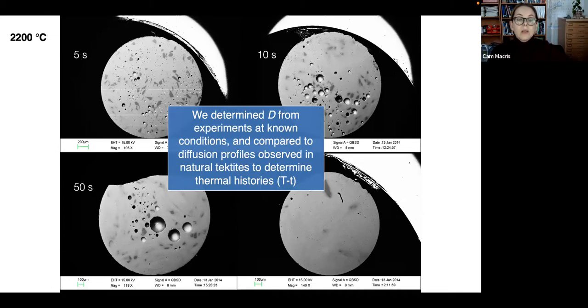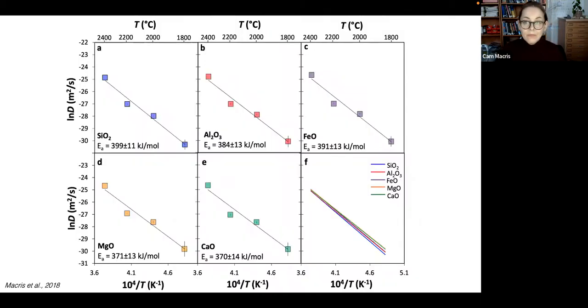So we used the compositional profiles taken from these experiments to determine the diffusivities at known conditions, and then compared with diffusion profiles in the natural tektites to determine thermal histories. And what I'm showing here are the diffusivities that we determined. So these are Arrhenius diagrams where the y-axis is the natural log of the diffusivity versus the reciprocal of temperature in Kelvin down here, and then in Celsius at the top here. And so all of the components are obeying the Arrhenius relationship. So this is the plot for silica, for Al2O3, FeO, and they all fall in a line when plotted this way, which means that the behavior that we're observing is definitely diffusively controlled.